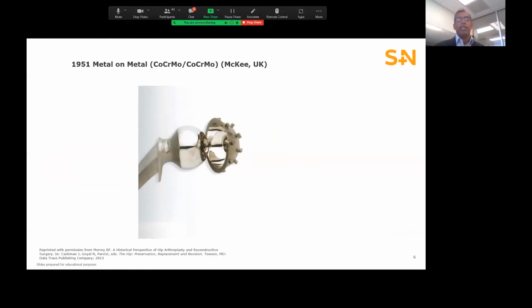And this is a design feature that continues to be used in modern designs. So while there have been previous attempts to resurface the acetabular component, the first device that performed relatively well after replacing both the femoral head and the acetabular surface was developed by McKee in 1951. It was a cobalt chrome on cobalt chrome device that incorporated spikes on the outside of the cup to promote mechanical fixation. Over the years, McKee and his collaborator Watson Farrar experimented with a number of different stabilization techniques. While the outcomes varied a bit, they were promising enough that the idea of total hip replacement appeared viable.